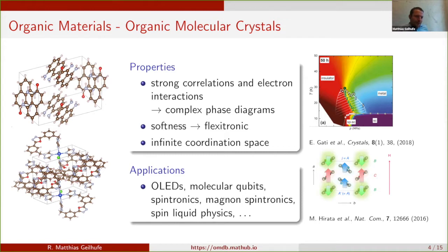So what is so interesting about these materials? One thing is that if you go back, for instance, to the organic molecular crystals, you have very, very different energy scales involved, namely that the electrons which mediate the binding of the atoms in the molecules, the binding energy and the hopping within the molecule, is much, much stronger than the hopping between the molecules. And that typically leads to super flat electronic bands, which we will see in a second.